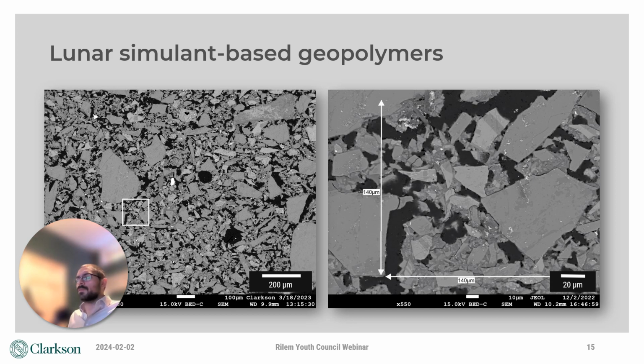Not all the geopolymers work well. Here's another sample with a different simulant and a different alkaline activator. And even in the very zoomed out view of the microstructure on the left, you can see that it's much coarser and more discontinuous than the previous one. In the close-up view on the right, you can see how the simulant particles are no longer well connected. The paste matrix between them is sparse and poorly refined, and this suggests to us that this combination of activator and simulant would perform poorly as a geopolymer.